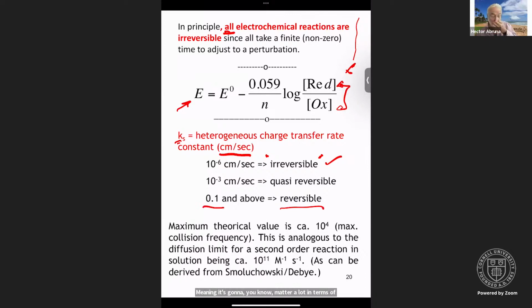In fact, whether a system is reversible or irreversible or behaves reversibly or irreversibly really depends on the time resolution of your experiment. For example, if you can do a charge injection experiment that takes, let's say, 10 nanoseconds, you're going to be sensitive to very, very fast processes. If, on the other hand, you're taking 5 seconds to measure the rate, even a very slow process will look fast on that time frame.